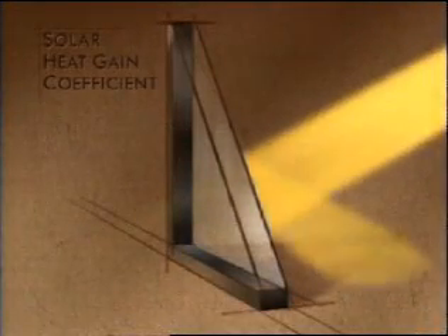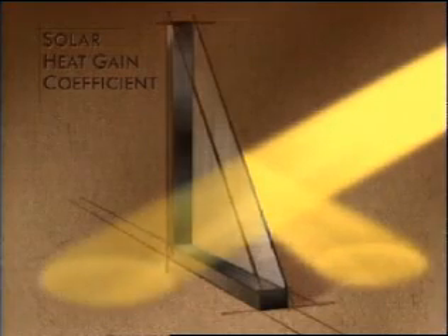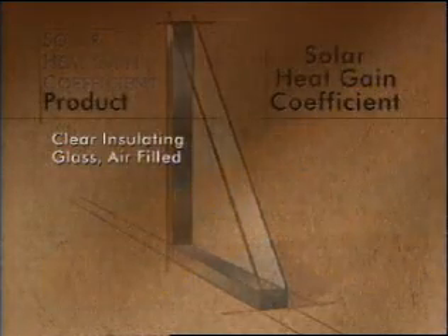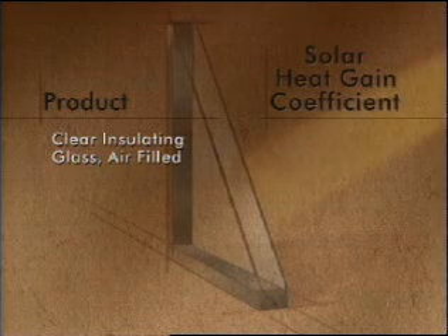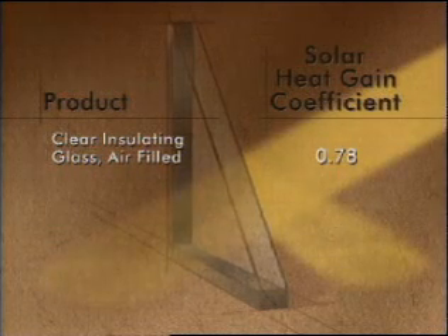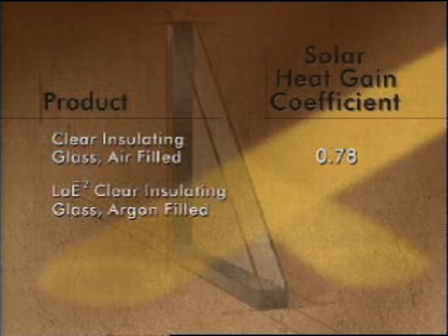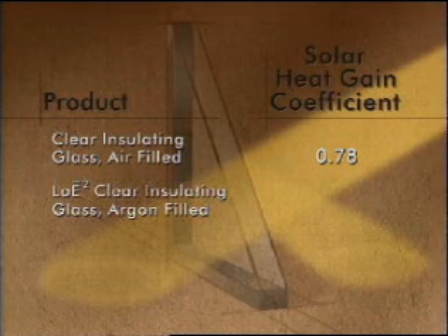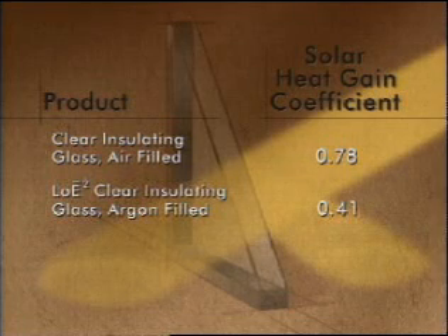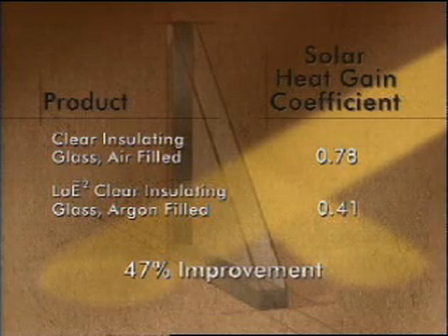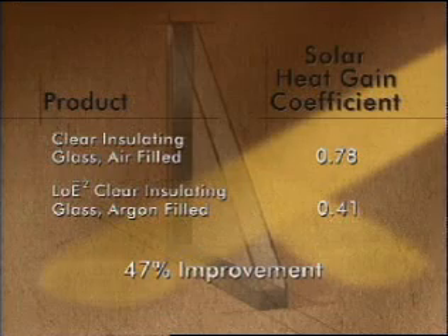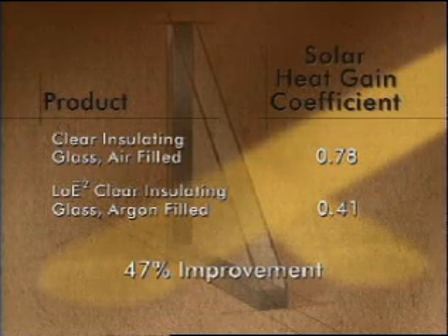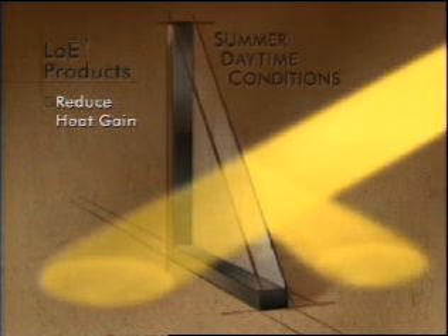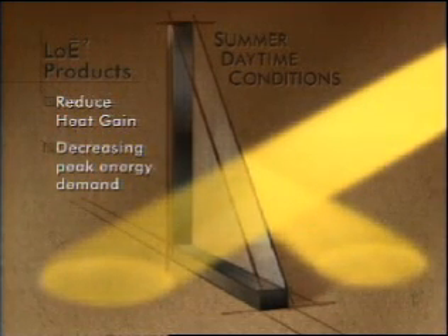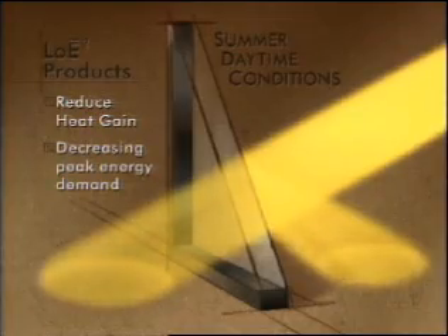The solar heat gain coefficient is the fraction of incident solar energy entering through the glass. A clear, air-filled insulating glass unit has a solar heat gain coefficient of 0.78. A LoE² argon-filled insulating glass unit has a solar heat gain coefficient of 0.41, a 47% improvement. The lower the number, the better the glass product is at keeping out the summer heat. LoE² coated glass products significantly reduce solar heat gain, decreasing peak energy demand which utilities experience during hot summertime conditions.